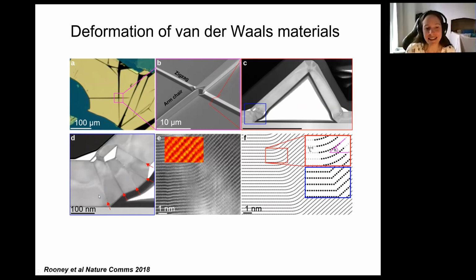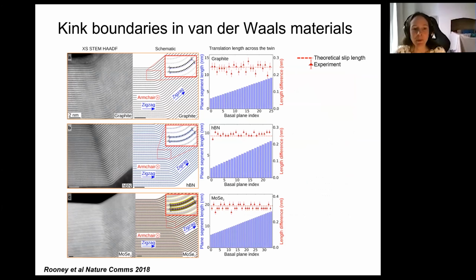What you see in D is a little bit like the schematics I showed you previously, whereby we've got regions of perfect crystal stacking separated by these line features. When we zoom in on the line features, we can see that they're associated with perfect stacking on either side, and then this local curvature. We can compare on the right here this curvature that we see to what we'd often expect to see in something like a metal, where we have an abrupt interface. So this boundary is a delocalized boundary rather than being abrupt as it would look in B.